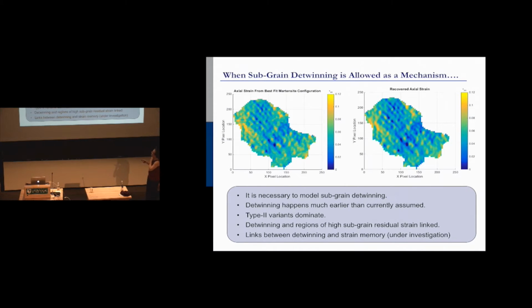And for a long time, the community has been saying that you don't have detwinning before the end of the stress plateau. We came out with this and said we think you do, and then actually a guy at Colorado School of Mines came out with a diffraction experiment that also showed that, yeah, you're getting detwinning in the middle of the stress plateau. The reason this is important is because you don't have to yank it all the way up to superplasticity in order to get this type of detwinning.